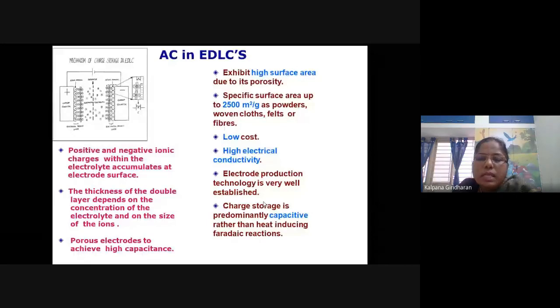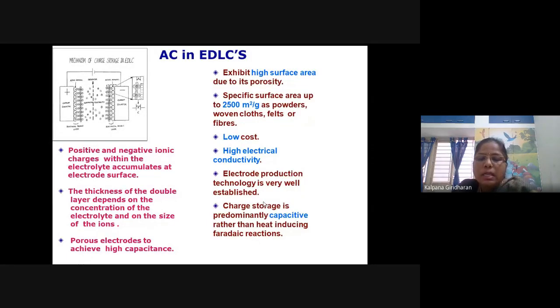It has high electrical conductivity. The electrode production technology is very well established, and charge storage is predominantly capacitive rather than heat inducing Faradic reactions. So in EDLC with this activated carbon, the thickness of the double layer depends on the concentration of the electrolyte and on the ion and the size of the ions. So the porous electrodes achieve high capacitance.